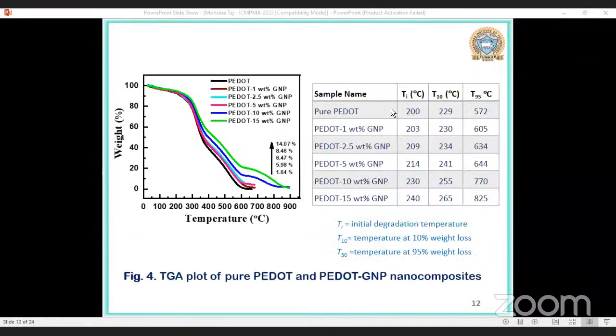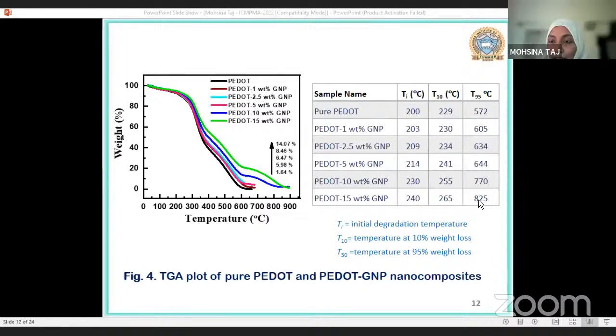Sir, here I have shown the initial degradation temperature of pure PEDOT was 200 degrees Celsius. But when we increase the graphene content to 15%, it increased to 240 degrees Celsius in initial degradation temperature. And also 95% of degradation in case of pure PEDOT is around 572 degrees Celsius. It increased to 825 degrees Celsius, sir.